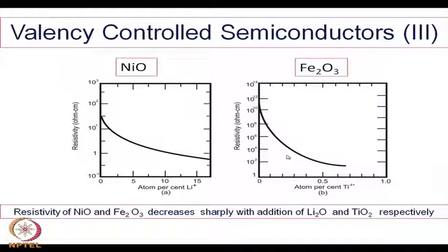of the oxides particularly, and these conductivities are independent of PO2 and mostly independent of temperature, because temperature of course will have some effect on the mobility. The concentration remains constant, but the mobility may change, and therefore there will be some change in conductivity as a result of temperature, but it will be completely independent of PO2. Well, the time is up.